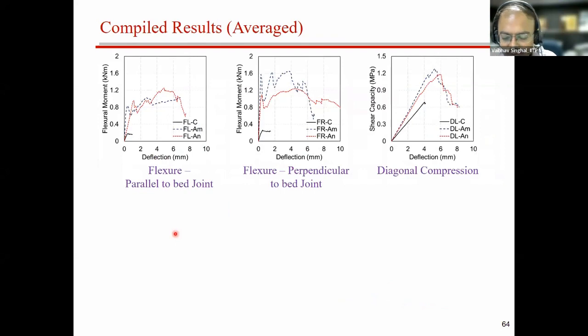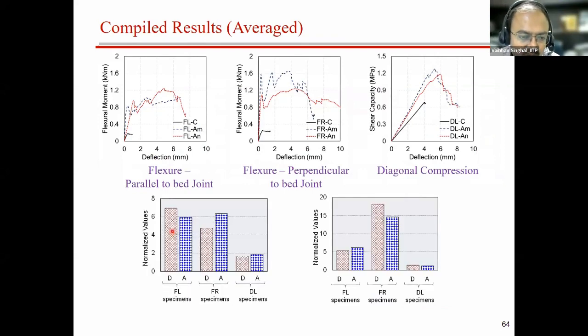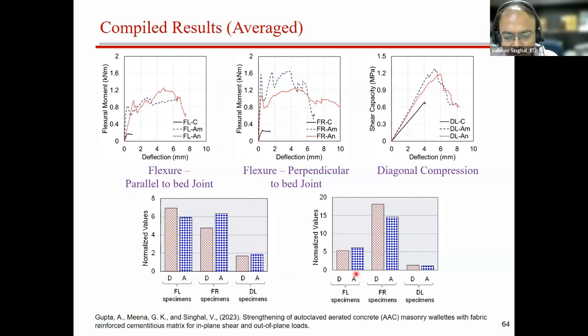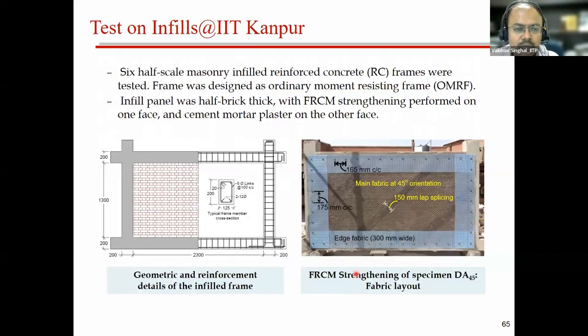Now, this is a comparison of the strengthening techniques. You can see here, D is the anchored one where we applied directly, and A is the adhesive mortar. Both bars look almost of similar height, so both give comparable results. The only problem with the adhesive mortar without anchor is that we have seen there can be debonding at different places. All these results have already been published, so if you are interested, you can go through them in detail.